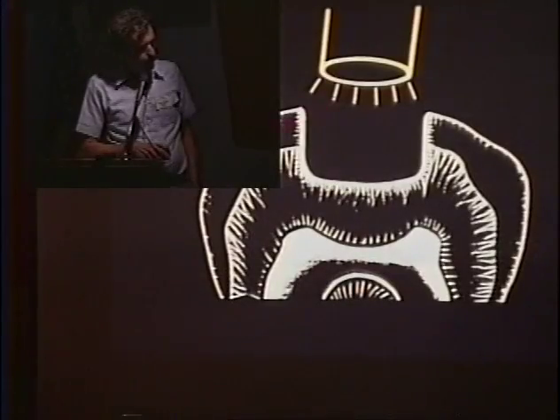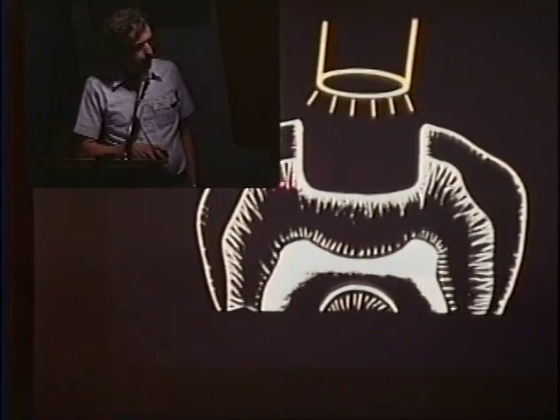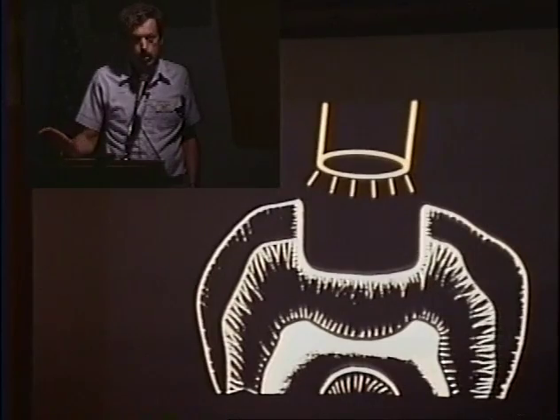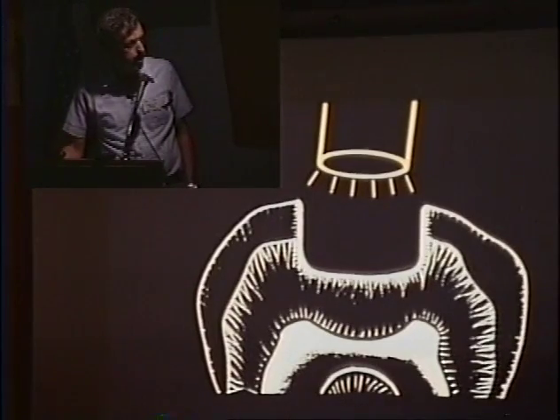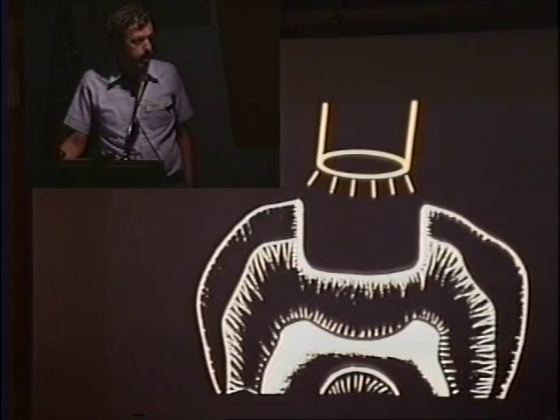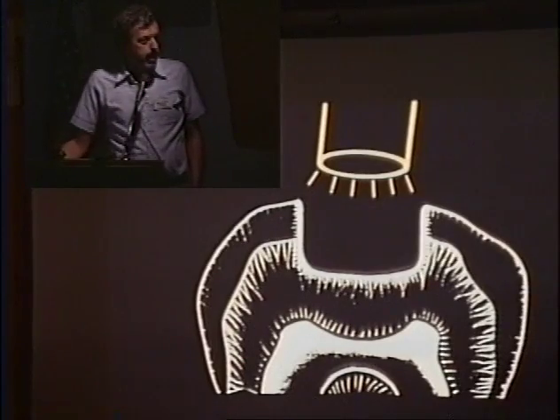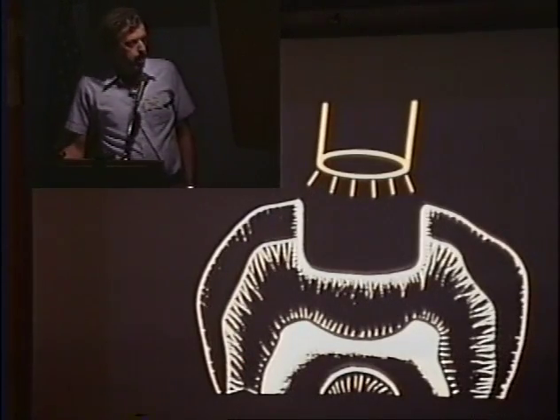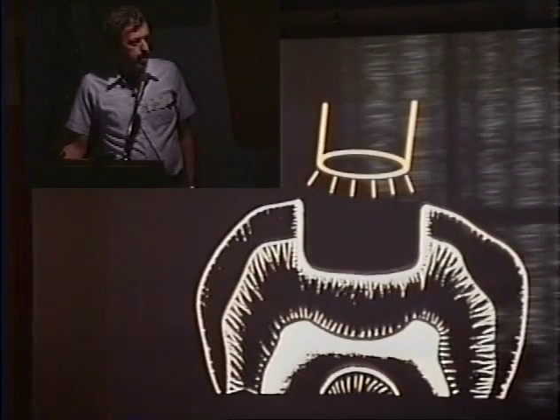All right, now let's think about putting in a filling here. So we go in and we cut a class 1 prep and put in a bonding agent. Now, a lot of different bonding agents out there. I have my own favorites, but what you need here is something that bonds enamel and bonds dentin, preferably with the same conditioning of the dentin and the enamel, and preferably with the same bonding agent on the dentin and enamel. Well, when you have that criteria, same conditioning agent and same bonding agent, that eliminates an awful lot of materials.